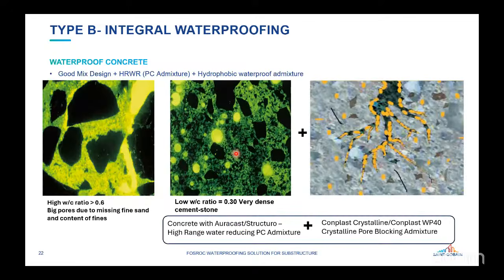So here the procedure is that we have to design a concrete with a very low water cement ratio to produce an integral waterproofing for the type B system. A concrete mix has to be designed with a very low water cement ratio. Once we reduce the water content in the concrete mix, the voids and the pores in the concrete will come down. And then in the same concrete mix, you add another admixture, which is basically a crystalline admixture, which will react with the products of cement hydration and form some insoluble crystals inside the body of the concrete, which will seal all the voids and pores inside the concrete.